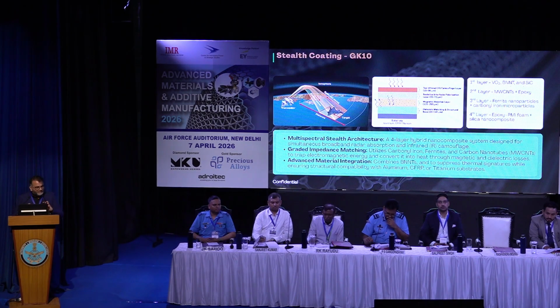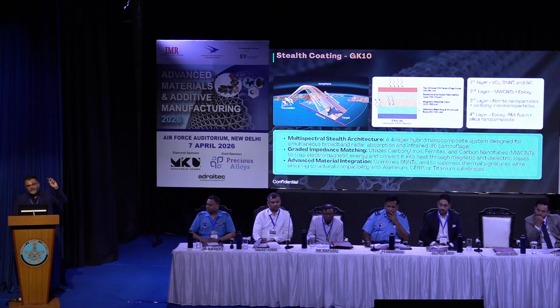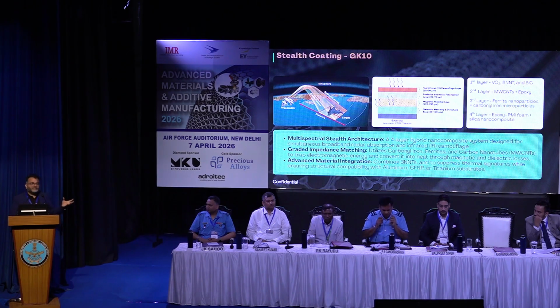In very layman language, photon particles are coming at some frequency. Now there are nanoparticles in these layers, and the bonds between nanoparticles, the electrons, are also moving at some frequency. So the photon frequency should match the electron moving frequency, and then you have resonance and you have eaten away the energy which the photon is carrying, so you are not detectable on the radars. This is the whole science behind it. Now you have to identify what bands are coming and what the frequency of those bands is, and how you can eat away that energy so that the reflection doesn't happen.